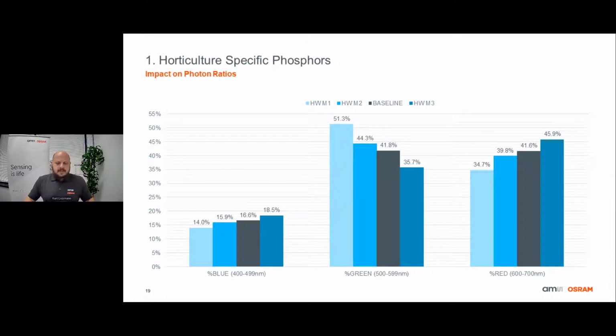So again, all of these solutions maintain that same red to blue photon ratio of 2.5 to 1. Depending on how you evaluate a spectrum, and in this case, we're evaluating the photon flux ratios in blue, green, and red, one could argue that all four of these spectrums are still pretty similar. The M1 and M2 solutions do have less overall red and blue content and more green content compared to the baseline solution, whereas the M3 solution has more red and more blue, but less green content. So one could argue that the M2 solution is probably the closest match when you look at all three wavelength bins.